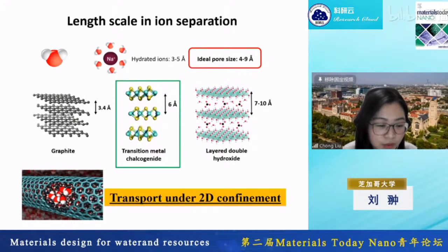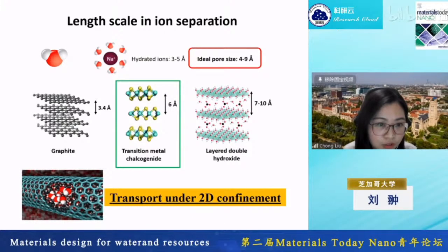So in this study, people have shown that if you give water a 1D confinement, water can actually transport much faster than in its bulk form. This is because the water is closely packed, like a semi-solid, and just goes through the channel fast without rotating a lot. Its hydrogen bonds don't have much interaction with the walls of the carbon nanotube.